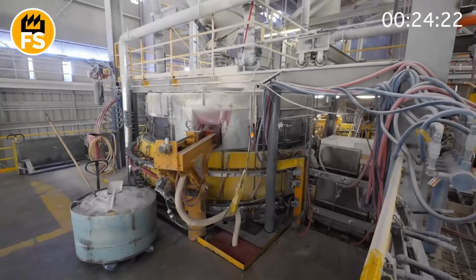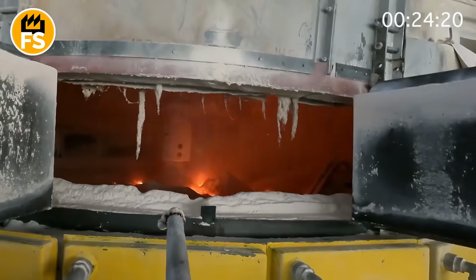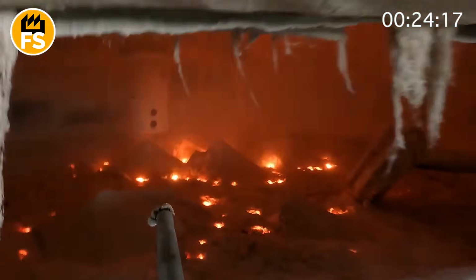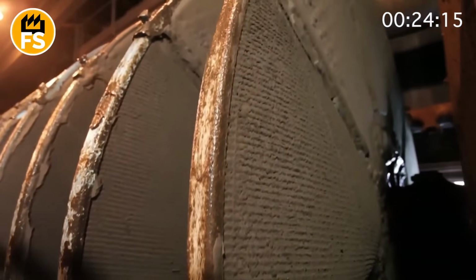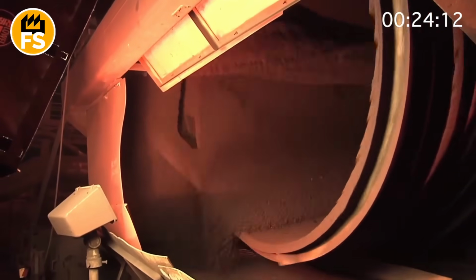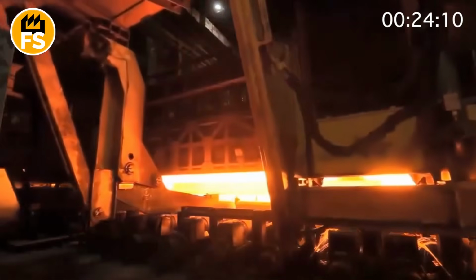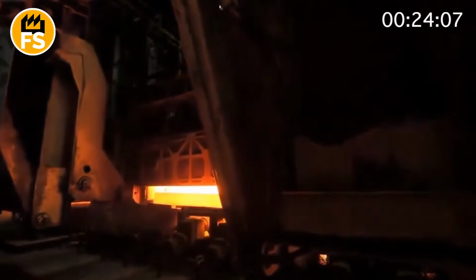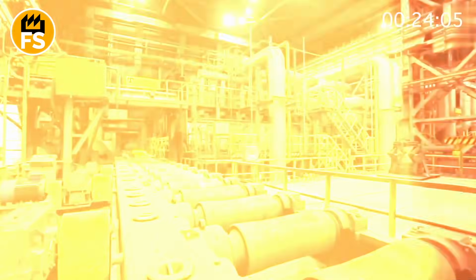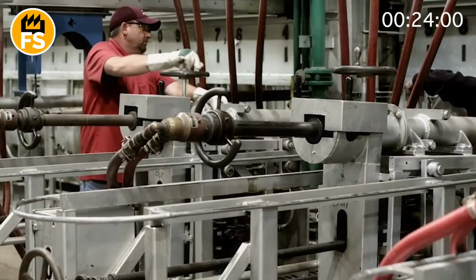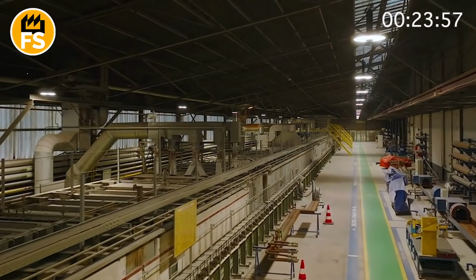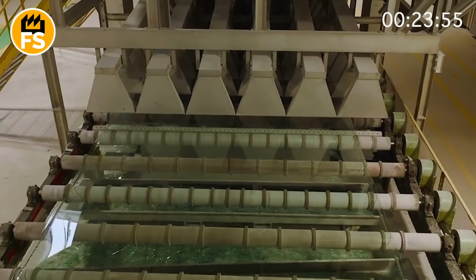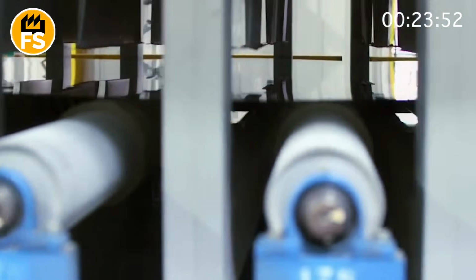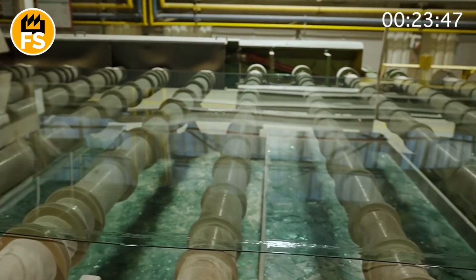After melting, the molten glass proceeds to the forming stage, most commonly performed using the float method in modern manufacturing. Feeding the molten glass. The liquid glass flows from the furnace onto a bath of molten tin. Due to the high density of tin, the molten glass spreads out uniformly across its surface. Under its own weight, the glass forms a perfectly even and smooth surface. Gradually lowering the temperature makes the glass grow solid. By the time it leaves the tin bath, it is ready for further processing. The float method allows the production of glass sheets with precise geometric parameters and a very high quality finish.